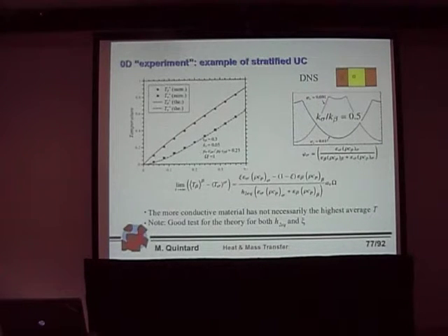And actually, the math gives the following result. So you have a difference that depends, of course, on omega. If there is no omega, there's no difference. And it depends on the heat capacities of the system, and it depends on the distribution coefficient and the exchange term in the system. There is a competition here between the heat that is exchanged between the two systems. The points here are DNS predictions, and the curves, red and blue curves, are the predictions. So it works